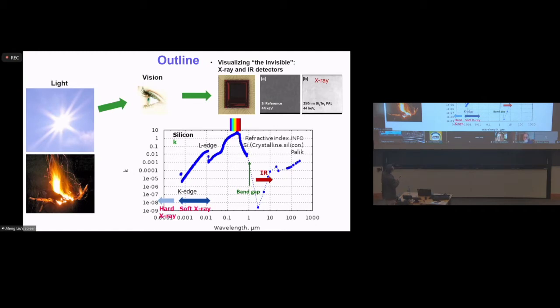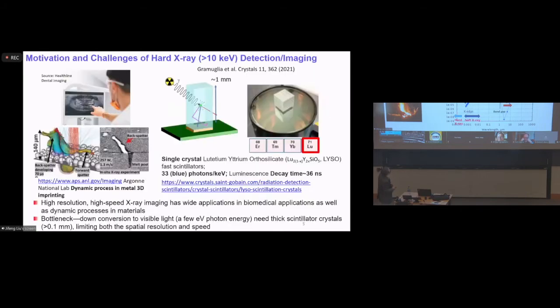In the very high energy regime, it's a similar case. Basically, the frequency of the X-ray photon is so high that there's no resonance in the silicon atoms anymore. Even if you look at the innermost core, which is the closest to the nuclei, because the atomic number of silicon is not very large, the attraction is not very strong. The binding energy is not very large, so essentially that resonance frequency is not high enough to resonate with those X-ray photons. So that's why, when we come to hard X-ray detection, the absorption of silicon also decreases. So the question is, can we integrate some other materials with silicon to make a universal X-ray, UV, IR image sensor extending to the full spectrum?